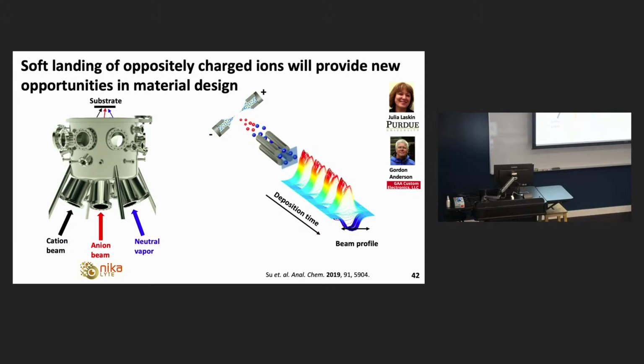Where are we headed in the future? Well, one of the limitations of the technique up to this point is that you deposit one polarity of ions. If it's a conductive surface, it's not a big deal. It discharges and you're fine. But if it's an insulating surface, you actually build up charge. And this can be enough to actually deflect your ion beam and stop your deposition.